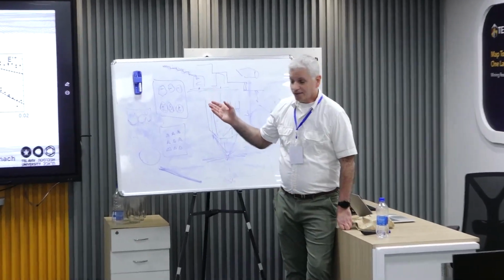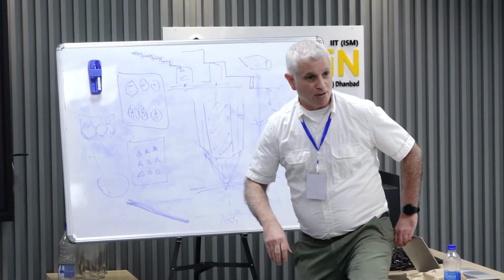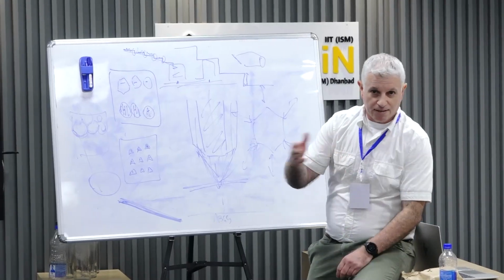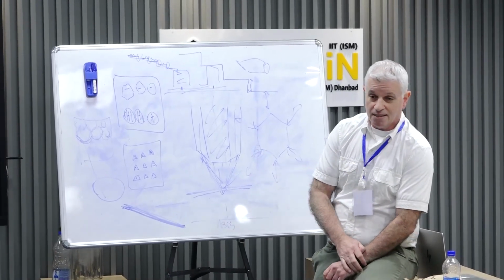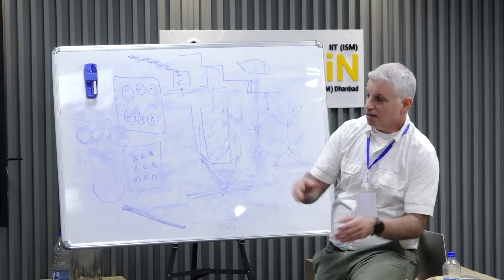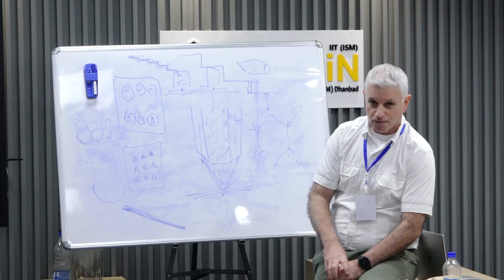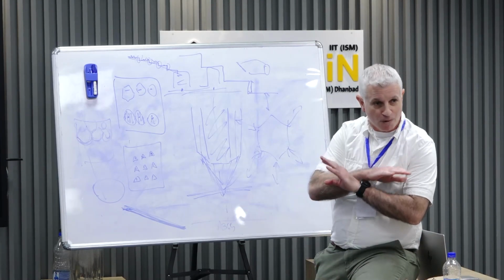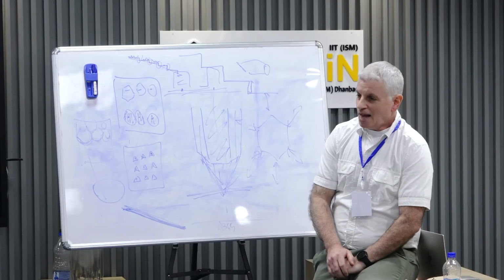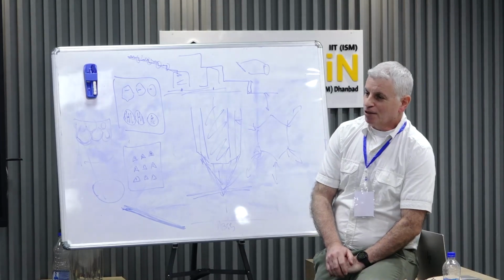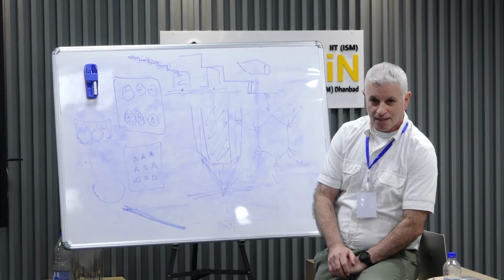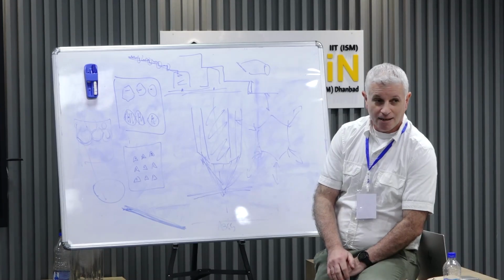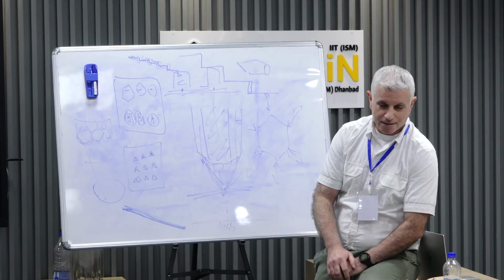In contrast to graphitic systems, where you have several peaks so you can compare between them, like the defects, the relative intensities of the G and D peaks, or the relative intensity of G and 2D, in hBN you have only one peak. When you reduce the hBN to a single layer, this signal is extremely weak.